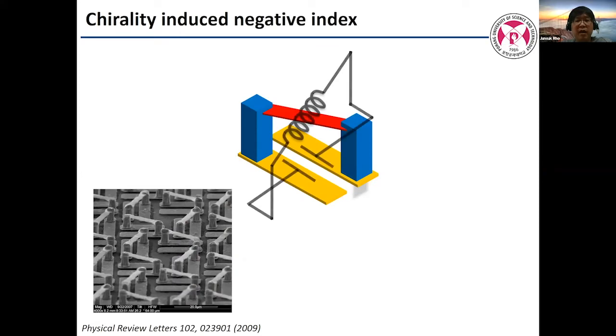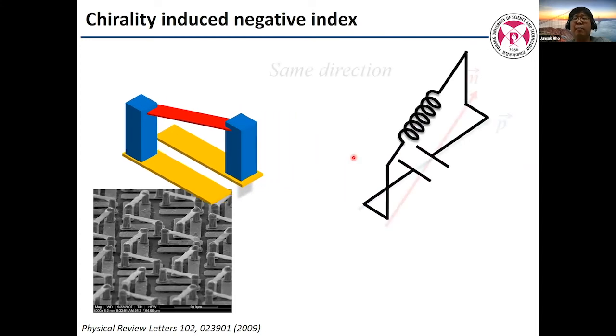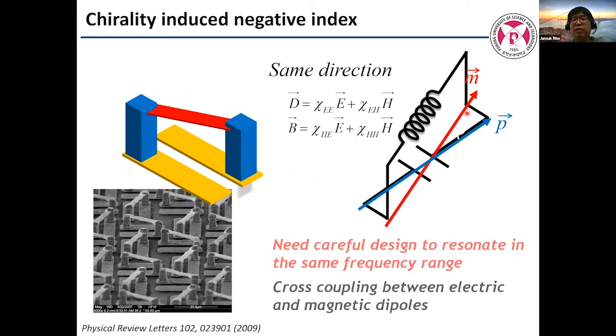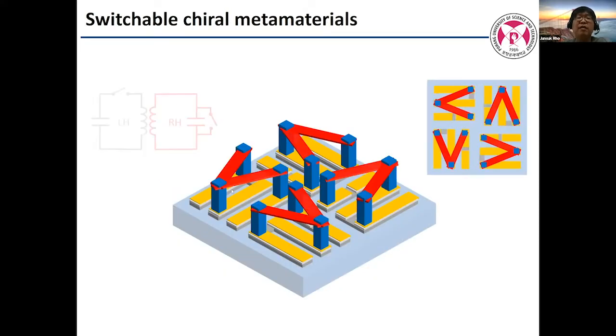And the first time, like 2009, we achieved such a three-dimensional chiral structure using microfabrication, and this is all made of gold, and it can be considered as a three-dimensional LC circuit. In this case, we can make coupling between the magnetic and electrical response. In that case, Snell's law is a little bit modified. So now n squared becomes epsilon mu plus something. This something comes from chirality. If this something becomes large enough and negative, then we can achieve a negative refractive index very easily.